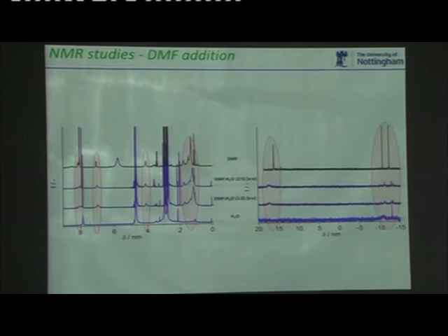A really interesting thing about this, though, is that as we look at the NMRs of the systems, if you look in DMF is where I showed you before, when I said phosphorus NMR is a brilliant tool. Look how good it is here. We've got 1 peak for the phosphonate groups and 2 peaks for the phosphates inside the POM. But if you look down here in water, in the same spectrum, those peaks are basically gone. As we add DMF to that, they grow back in.